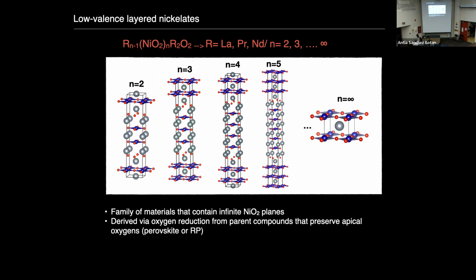This up here is the general formula for this family of materials, where R is a rare earth ion that can be lanthanum, praseodymium, or neodymium. And this n factor that you see appearing in a couple of places tells you how many of those nickel-oxygen 2 planes you have along the z-axis. So for n equals 2, you have the bilayer material. For n equals 3, the trilayer material, and so on, all the way up to the infinite layer member of the series.